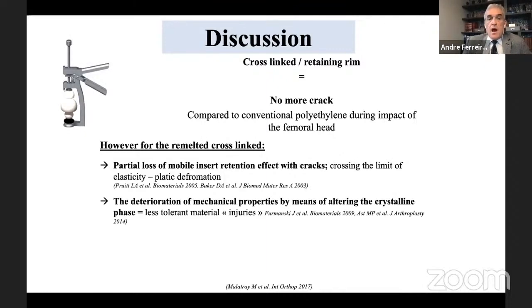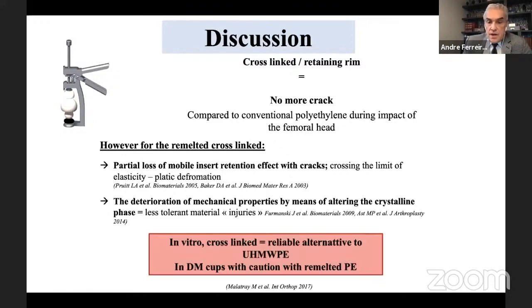However, for the remelted cross-linked polyethylene, there was a partial loss of the mobile insert's retentive effect with cracks, because they crossed the limit of elasticity and plastic deformation. So the deterioration of mechanical properties by altering the crystalline phase leads to a risk of intra-prosthetic dislocation. So in vitro, cross-link is a very reliable alternative to standard polyethylene, but with caution with the remelted polyethylene. So annealed seems to be superior to remelted one.